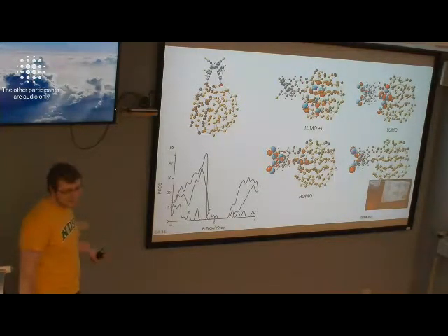Oh, okay. So it's definitely not coming just from the electronic structure, maybe from these artificial charge transfer states, which would be immediately eliminated if that was the problem. Putting solvent should really eliminate this. However, if these states come in due to conformational changes, and in solvent the conformation might be different, right? Yeah. So it looks like optimization in solvent is still needed as well. So it's actually number 5 probably.